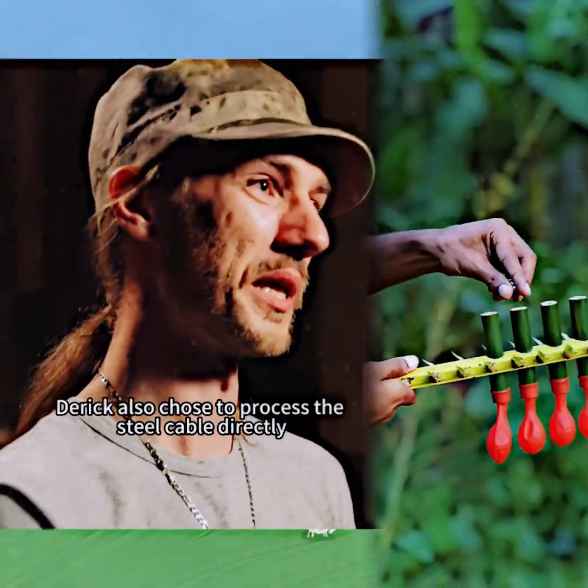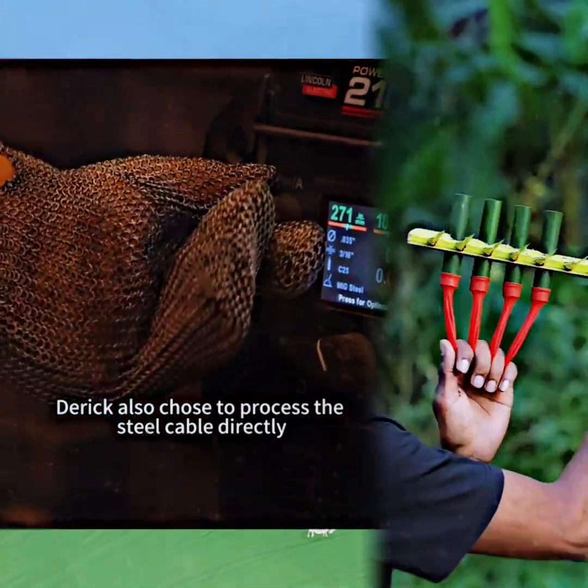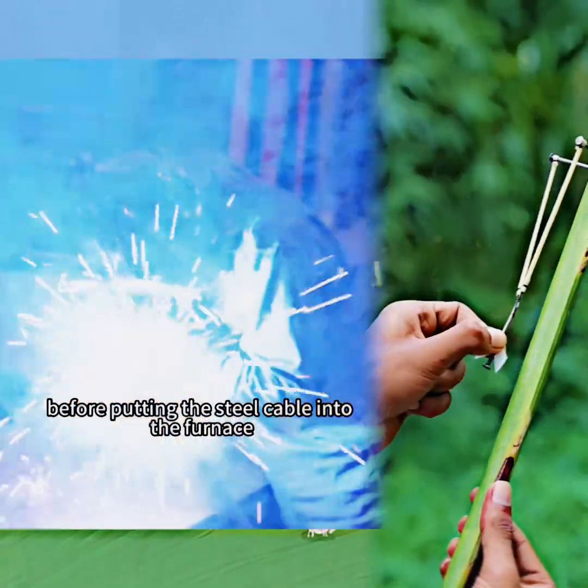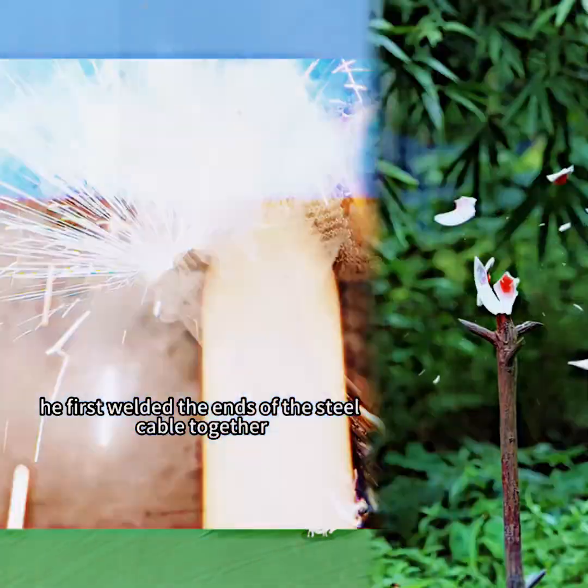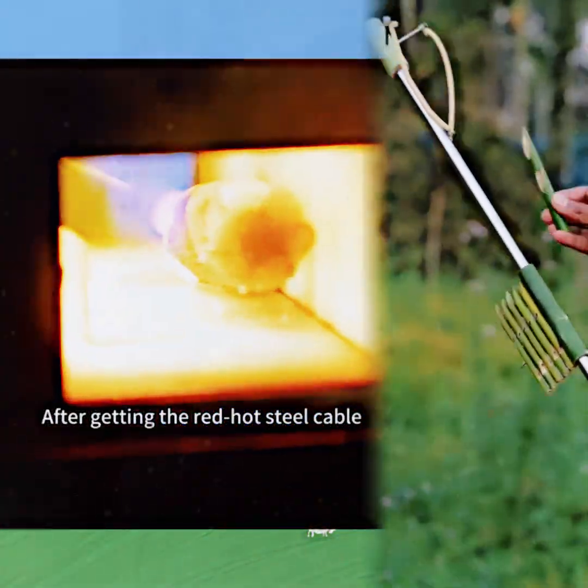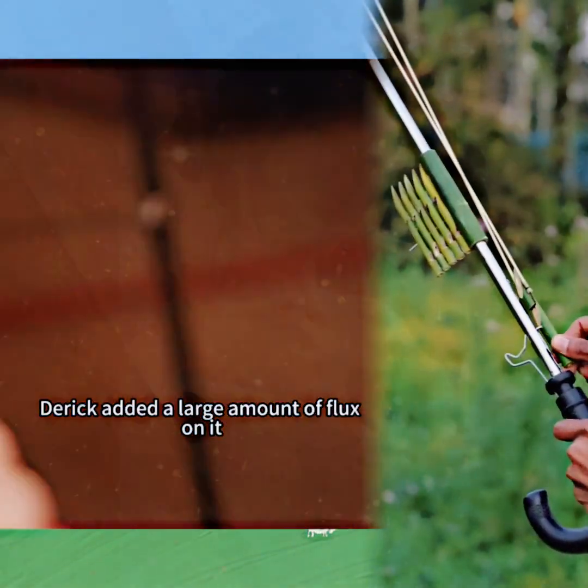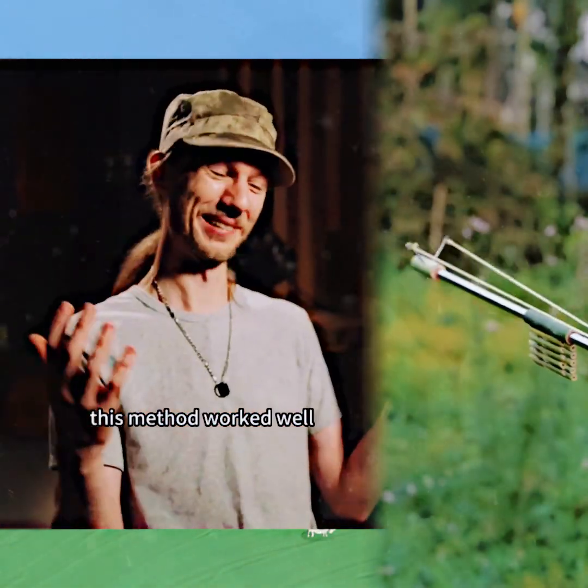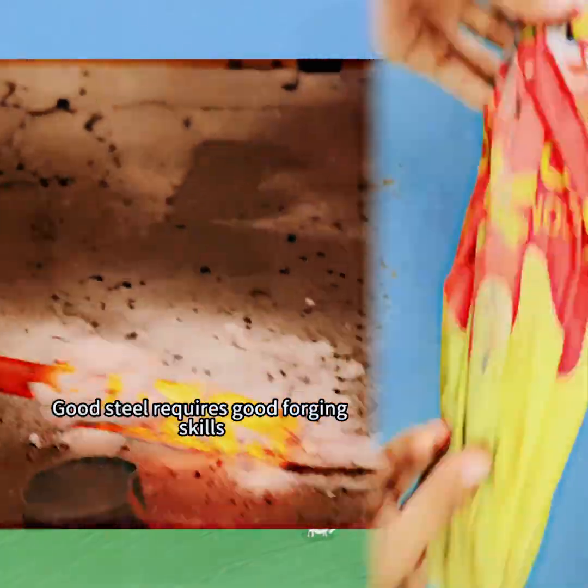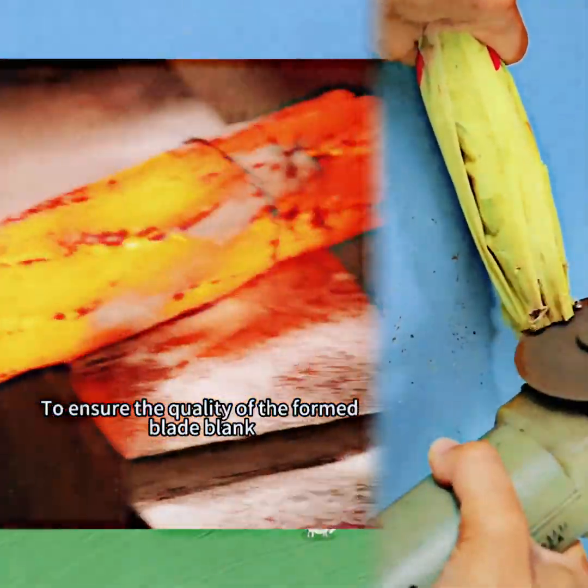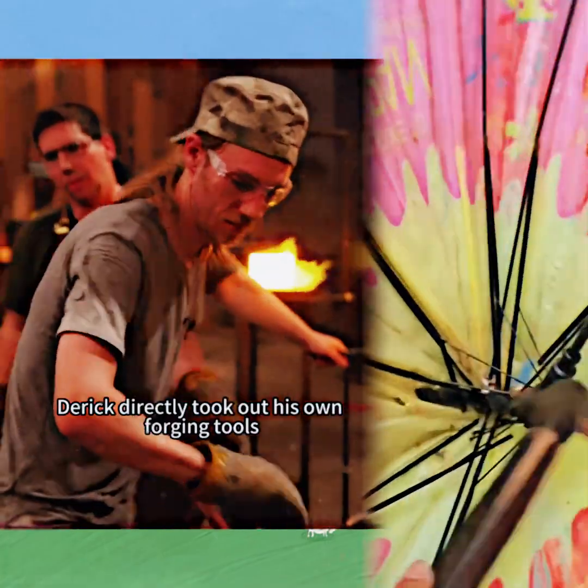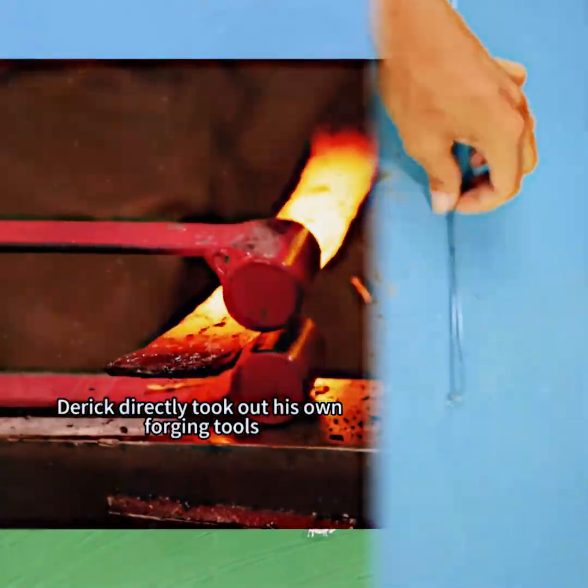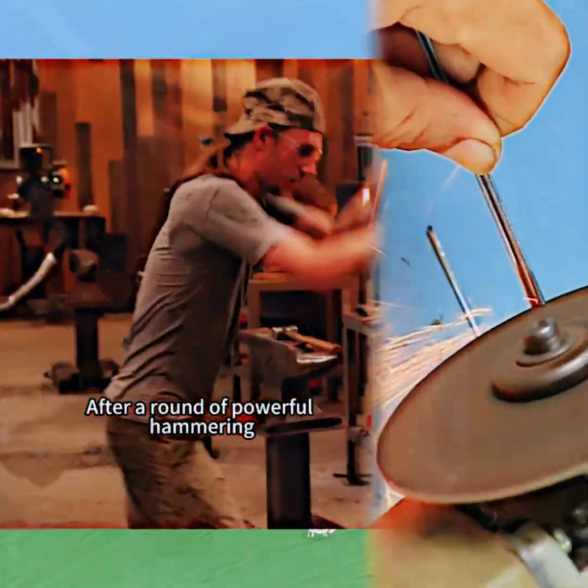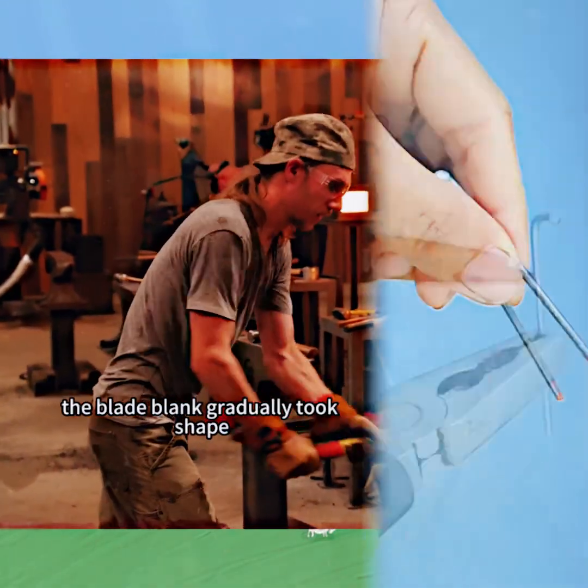On the other side, Derick also chose to process the steel cable directly. Unlike DJ, before putting the steel cable into the furnace, he first welded the ends of the steel cable together. After getting the red-hot steel cable, Derick added a large amount of flux on it. Fortunately, this method worked well. He successfully got a good steel billet. Good steel requires good forging skills. To ensure the quality of the formed blade blank, Derick directly took out his own forging tools. He stretched and lengthened the blade blank. After a round of powerful hammering, the blade blank gradually took shape.